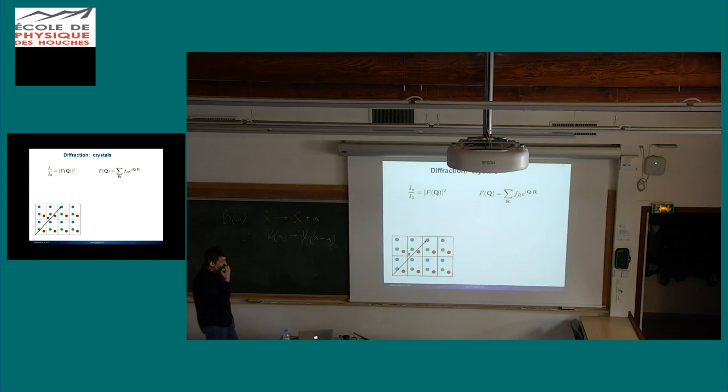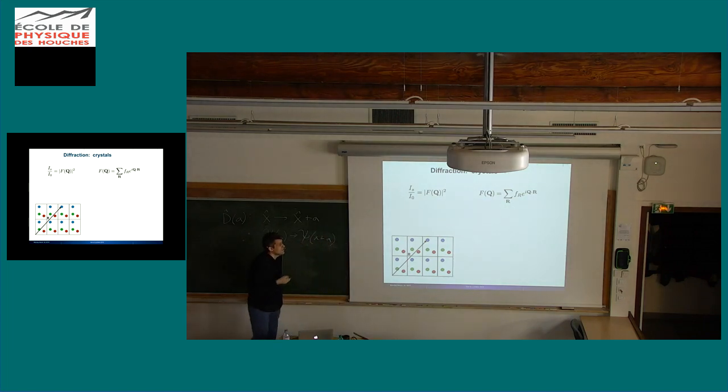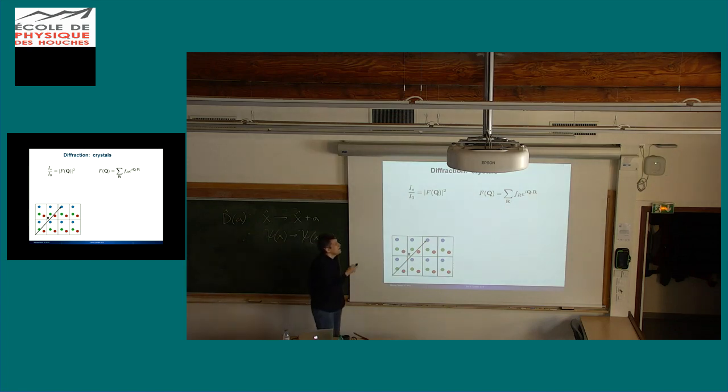All right, so to a fairly good approximation, the intensity that you measure with X-ray diffraction is given by the so-called scattering factor F squared. The magnitude of the electric field goes as F, and then we take the magnitude squared because we typically can only measure the intensity. This F can be broken down again, to a fairly good approximation, at least for reasonably heavy atoms, as a sum of atomic scattering factors. These f are scattering factors for each atom, and these are phase factors that take care of the fact that you have superposition between different electric field oscillations.